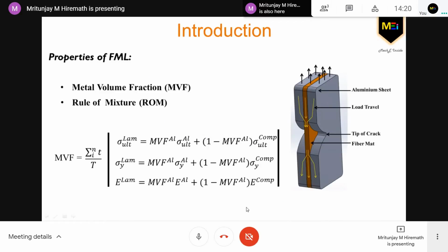Coming to its properties, they depend on the metal volume fraction in the rule of mixtures. On the right hand side, you can see how the load is carried by the glass fiber whenever a crack is present in the laminate. The glass fiber acts as a crack bridging mechanism and carries the maximum load whenever a crack is present in the aluminum. The metal volume fraction heavily depends on the aluminum thickness over its contribution to the whole laminate.